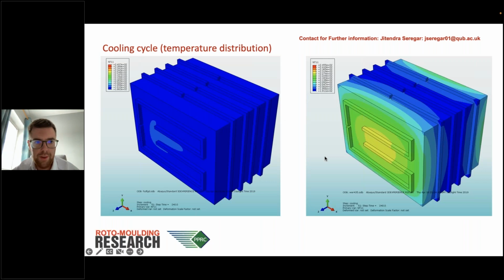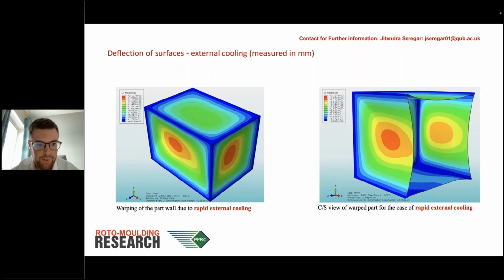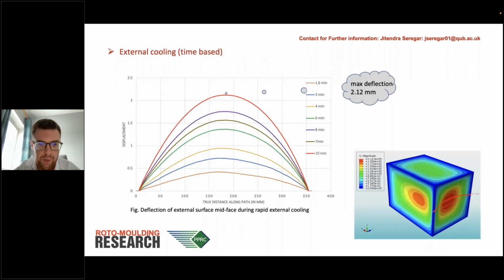And he is able to simulate the temperature change across the mold, which then can be translated into a warpage plot of these parts. So in this case, what you're seeing is a rapid external cooling effect, which was a spray of water onto the surface, and he's able to plot down the displacement of the parts, and in this case he's gotten a 2.12 millimeter deflection.